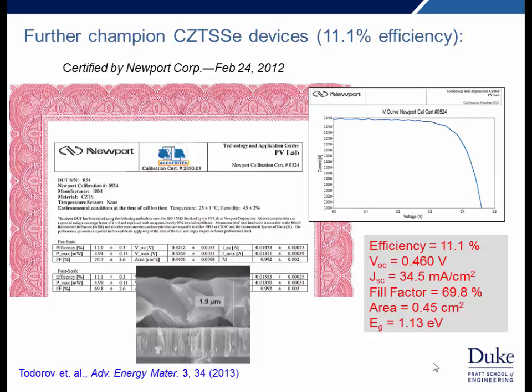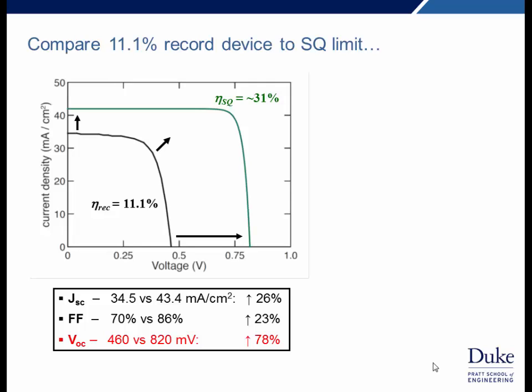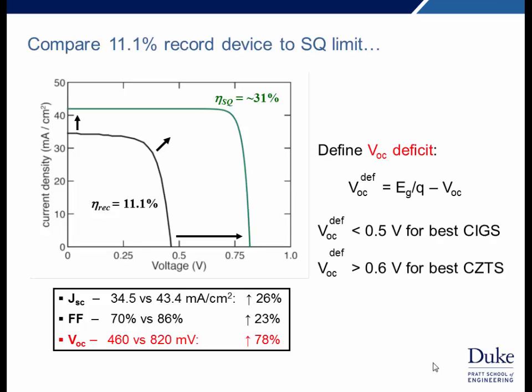The improvement came predominantly from short circuit current and fill factor. The open circuit voltage remained under 0.5 volts. And in fact, if we compare our JV curve for our best device at the time with the Shockley-Queisser limit, the short circuit current and the fill factor are not doing too badly. However, clearly the open circuit voltage is suffering quite severely. And any attempt to significantly enhance the performance in CZTS needs to address this issue.